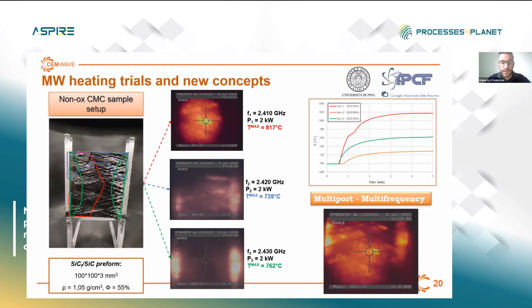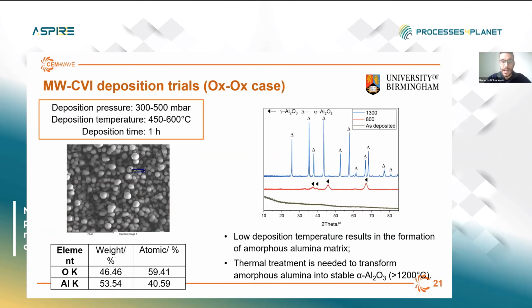Whereas we just could heat and infiltrate later the material by looking for a different operating frequency, aiming at the end, of course, to the full infiltration of our materials. As for the oxide-oxide materials, I present you the first results derived from microwave CVI deposition trials, which have been successfully carried out at the University of Birmingham, depositing the desired alumina matrix. Currently, optimization works are being dedicated in order to maximize the deposition rates while being able to improve the quality of the alumina matrix desired.